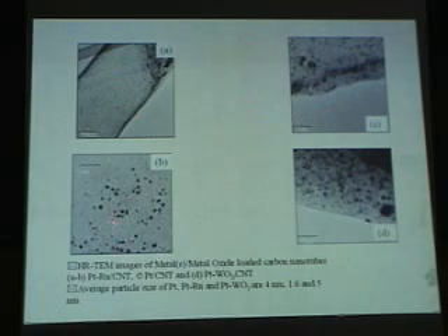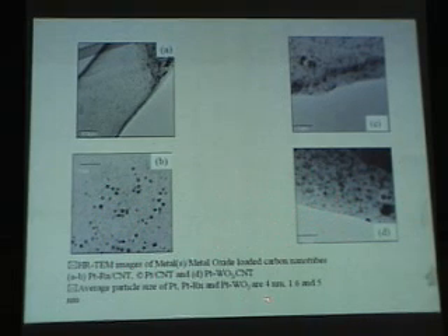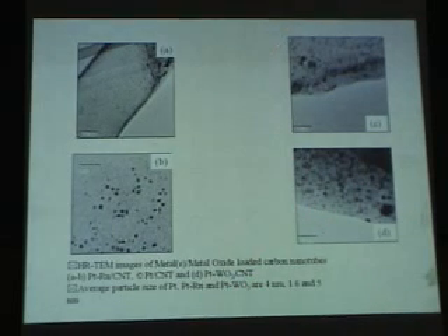Now loaded, platinum is loaded. Now you see beautifully how it is now. Now when compared to the polyphenol acetylene, now polypyrrole, you see how beautifully the platinum particles are loaded and dispersed. You can see here also the efficiency of the loading. Here you see we have now reduced the platinum tungsten oxide. If you remember, we could not reduce it to below 10 nanometers. We have reduced it to 4 nanometers here now. If we can reduce it by one more order, to 2 nanometers, the efficiency can go up.